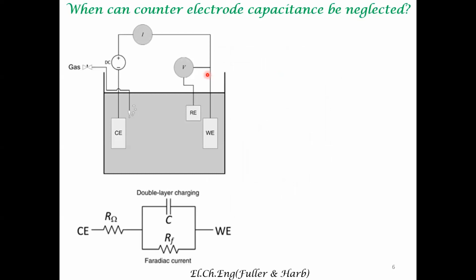There is one final issue with respect to this lecture. If you remember, we started all these experimental measurements by mentioning a three-electrode setup. So even though the action is at the working electrode, the current at the working electrode is compensated by the current at the counter electrode, and there's no current that passes through the reference electrode, ideally. So in the equivalent circuit here, we have neglected the features of the double layer corresponding to the counter electrode-electrolyte interface. Why is that so?